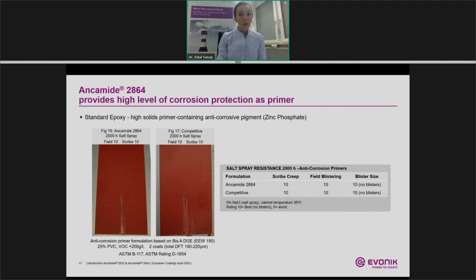Here, we tested the corrosion protection behavior in a model anti-corrosive formulation, which you can find with details again in our TDS. Then we ran the salt spray test for 2000 hours. After 2000 hours, we didn't observe any damage or blisters on the panels. In this case, the corrosion resistance performance is comparable with the competitive curing agents, and those achieve the highest rating.